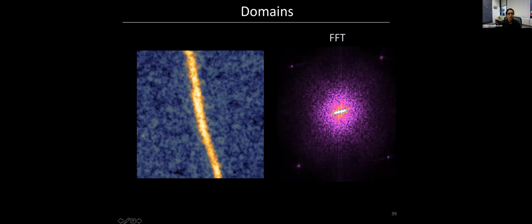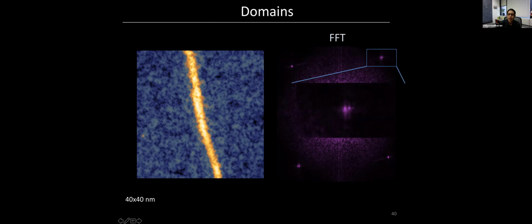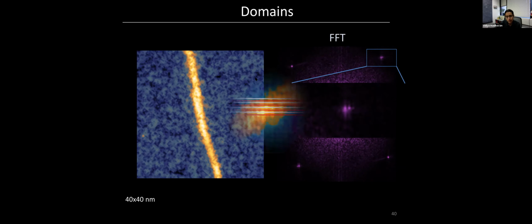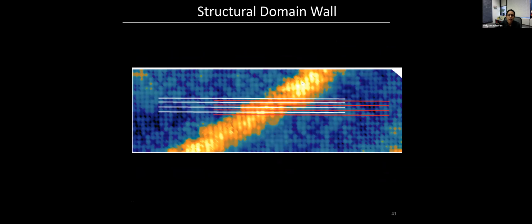One thing is you take a region, a topography like this, and you do a Fourier transform, you immediately see that, if you zoom in here, this is the atomic lattice. And the fact is that you have these two dots. The presence of a split peak in the Fourier transform indicates that these two sides are actually two different domains. It doesn't tell you there's a pi phase shift.